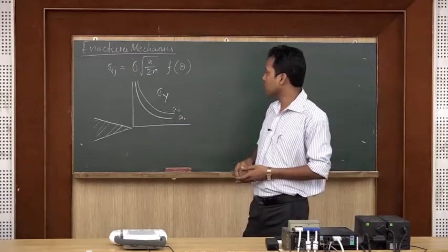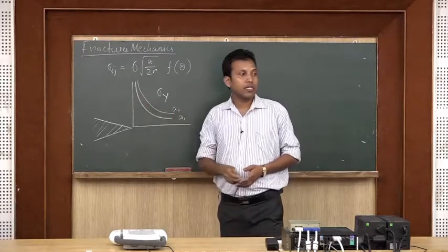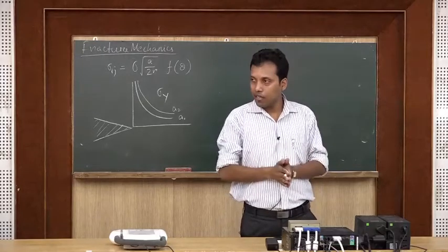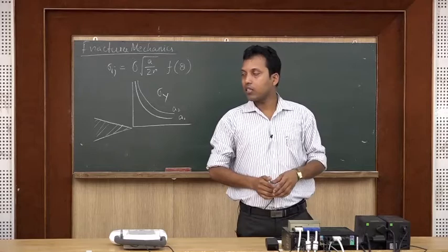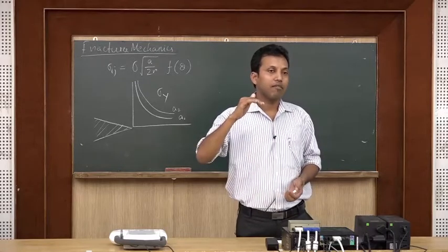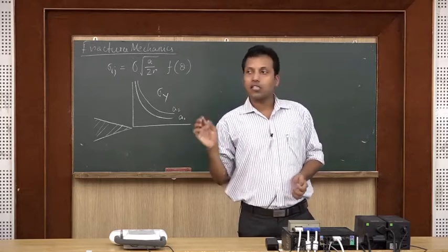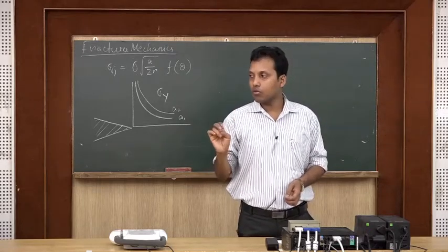Those things we have seen. So up to some certain extent the material must be having some high stress field, and that may well be above the yield strength level of the material. So in a material something which is known as plastic zone will form, okay.